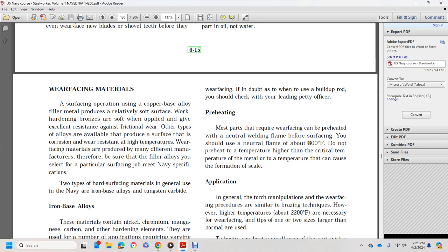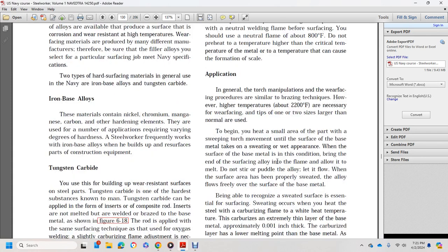Preheating. Parts requiring wear facing should be preheated with a neutral welding flame before surfacing, to about 800 degrees Fahrenheit. Do not preheat to a higher temperature than the critical temperature of the metal, or a temperature that can cause the formation of scale. Application in general: the torch manipulation for wear facing is similar to brazing techniques, using a high temperature of about 2200 degrees Fahrenheit. Use wear facing tips about two sizes larger than normally used. If you are going to heat a small area of the part, sweep the torch over the base metal until it takes on a sweated, wet appearance. Then, with the surface in this condition, bring the end of the surfacing alloy into the flame and allow it to melt.